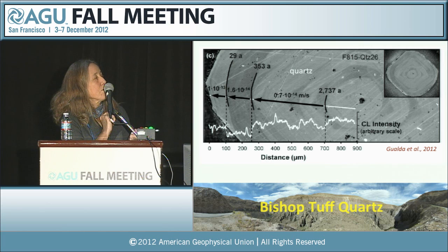Gualda and others have just recently published a paper looking at the mineral quartz from the Bishop Tuff, and they've taken advantage of the well-known variation in cathodoluminescence intensity within these quartz crystals, which can be correlated with titanium concentrations, and then use the diffusion rate of titanium to get at, again, magmatic timescales and rates of processes.